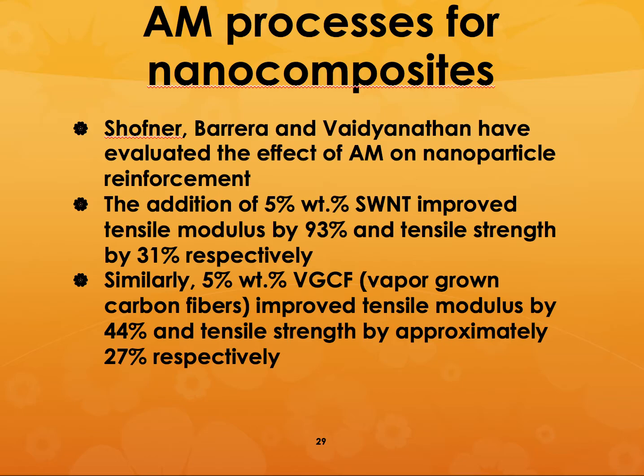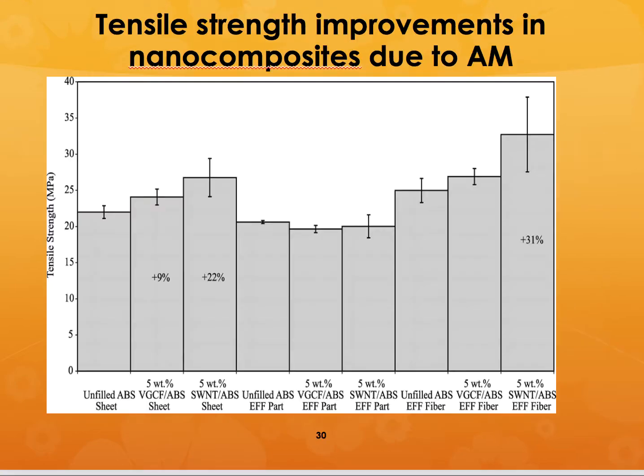So you can see that adding so much of nanotubes and introducing so much complexity in the processing doesn't really improve the properties a whole lot. But just adding 5% vapor grown carbon fibers improve the tensile modulus by 44% and tensile strength by approximately 27%. So we found that vapor grown carbon fibers, which are much cheaper than single wall nanotubes, and are not as complicated to process compared to the nanotubes, did give us something comparable. Not as good, but pretty comparable.